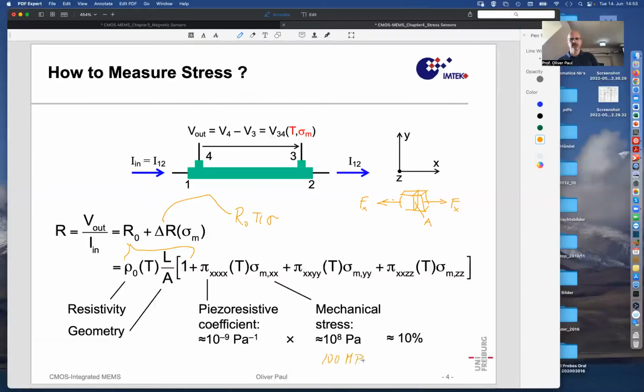And so it's easy to see that under a stress of 100 megapascal with a realistic piezoresistive coefficient of 10 to the minus 9, we obtain a 10% change in resistance. That's appreciable. And that also shows you that this idea of elastic deformation is not correct, because you can't under 100 megapascal stretch silicon by 10%, making L 10% longer to make the resistance 10% longer. It will move hardly a fraction of a percent, and therefore geometrically would expect a fraction of a percent of resistive change, but because of the band structure effect, you get 10%. So that's the magic about semiconductors, to have these large piezoresistive effects, much larger than metals, who only benefit of the geometrical effect. That's why silicon has become a wonderful sensor material for mechanical measurement.